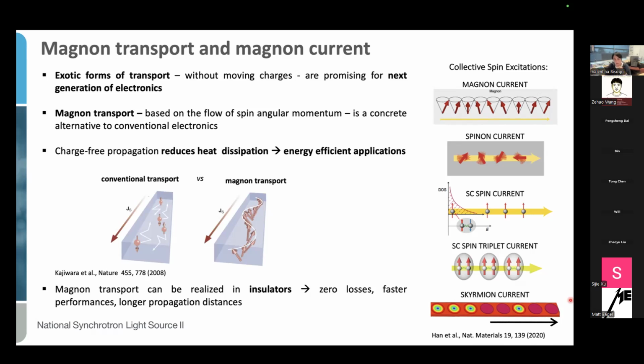So what is the key point behind this type of transport? Without moving charges, essentially we benefit from reduced heat dissipation. In conventional transport, electrons convey energy and go around the material, but at the same time they also scatter into each other and into other quasi-particles like phonons, causing a dissipation of energy by, for example, Joule heating. But if we get rid of the moving charges and base our transport simply on the flow of the spin angular momentum, as represented here by this Magnon wave, we gain a lot in terms of reduced heat dissipation. Therefore, we have an option for very energy-efficient transport.